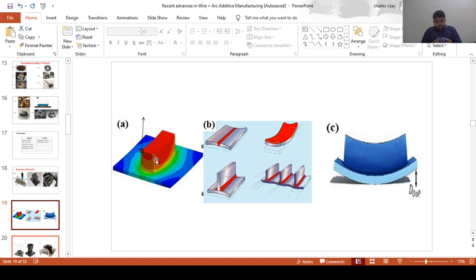Repeated melting and solidification will take place, so thermal induced stresses will form in the base plate, which may lead to base plate distortion. This distortion is the most common problem, but it could be avoided by using a base plate that is thick enough, like a minimum of 15 to 20 mm thick. If you use a very thick base plate, this kind of distortion could be greatly avoided.